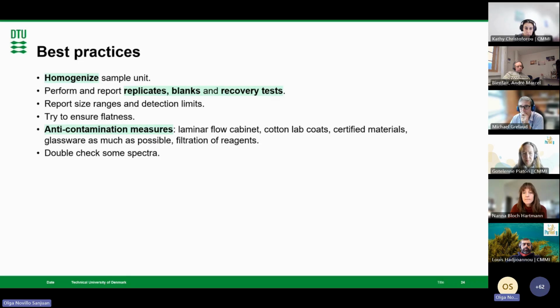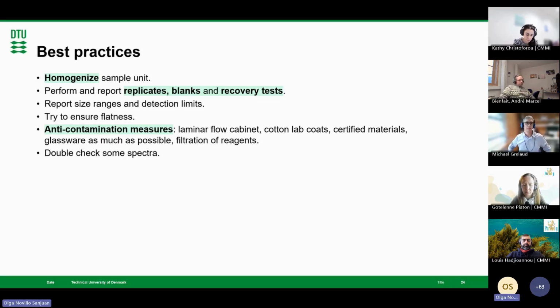Then always report your size range and detection limit. Try to ensure flatness of the sample in the case of the LDIR, because it can make a difference, and sometimes it's challenging. And always, of course, take anti-contamination measures: work in a laminar flow cabinet if possible, wear cotton lab coats, use certified materials or reference materials if possible. And again, glassware, filtration of reagents, this is common to all of the techniques, really.